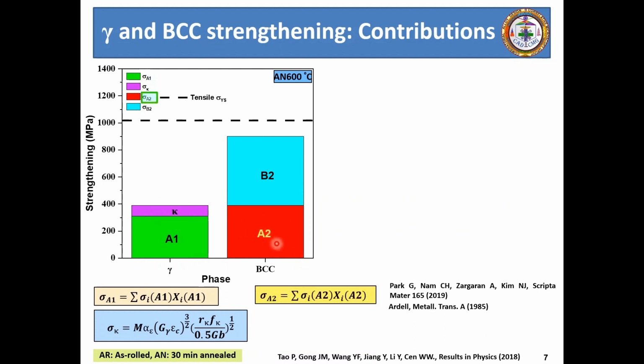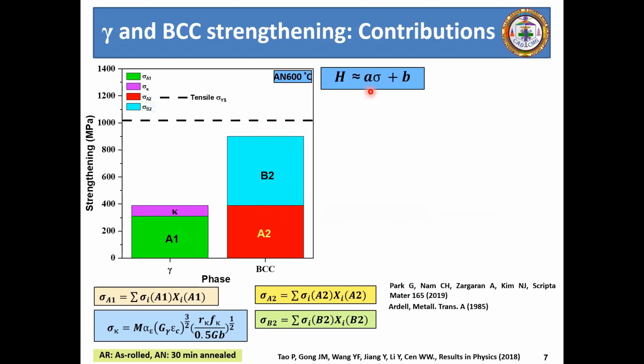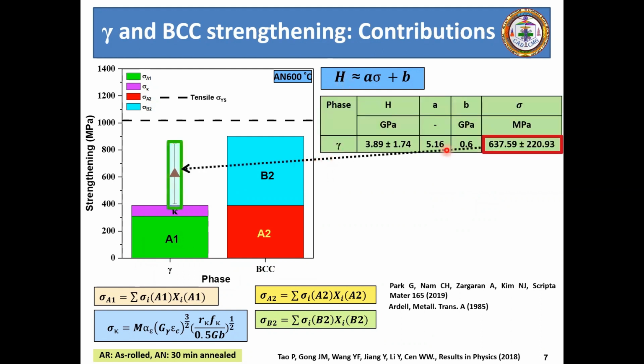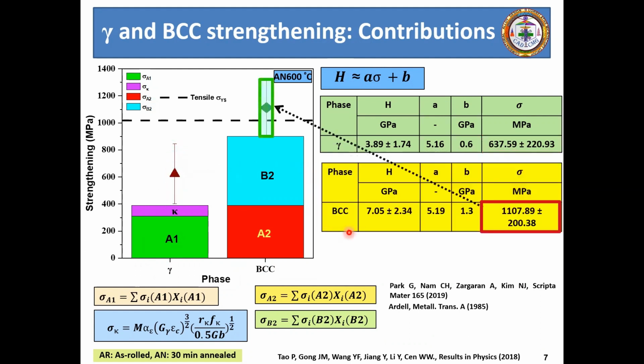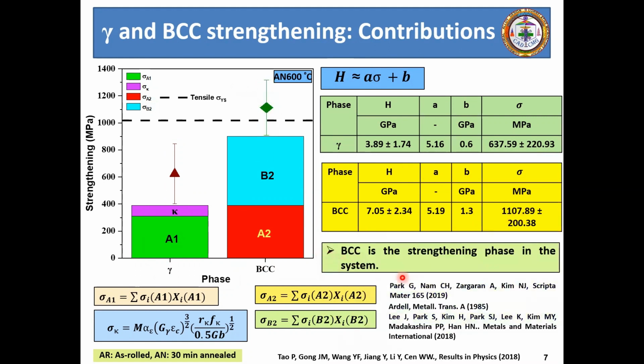Then the sigma A2 represents here the solid solution strengthening contribution from the disordered BCC or the A2 phase, and the sigma B2 here represents the strengthening contributions from the B2 precipitates localized within the BCC phase. Now, when we further try to validate these results by finding out the values of sigma gamma and sigma BCC based on their nanoindentation hardness, we can clearly see that the gamma contributes nearly around 638 MPa to the uniaxial tensile yield strength, whereas the BCC contributes nearly around 1.1 GPa. So this implies that the BCC is the strengthening phase in the system.